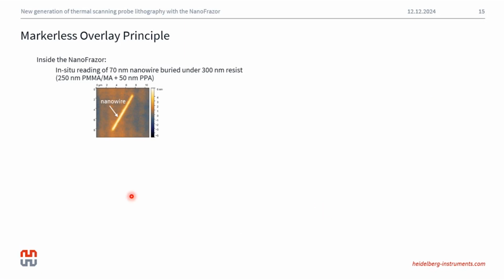And the way we do so is by roughly locating the region of interest where the nanowire or the flake could be located. We move to this region with our tip, and we launch the reading of the topography of this region in a damage-free way with the tip at room temperature. In this way, very fine topographical features like nanowires or 2D flakes can be detected with a very high accuracy, even if they are buried under thick resists. For example, this is an indium antimonide nanowire that is only 70 nanometers in diameter, which is buried under a bilayer resist stack of 300 nanometers in total.